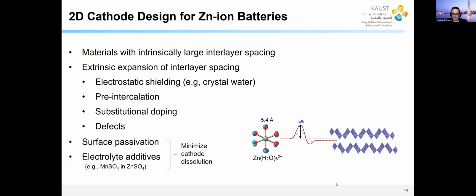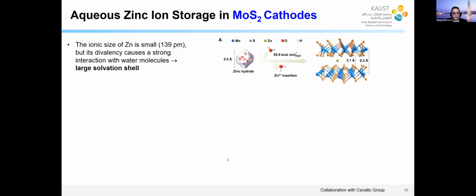So the problem, as I mentioned, is you are not intercalating only the zinc ion. You are intercalating a zinc ion solvated by 6 water molecules. So you have a species here that's 5.4 angstrom in size. It means basically much bigger than the zinc ion size. So let's see how the molysulfide fares with this. If you look at molysulfide, actually the spacing between the layers is only 3.1 angstrom. Okay, so if you wanted to insert zinc, which is solvated by these water molecules, into the molysulfide, it's a very difficult thing to do.